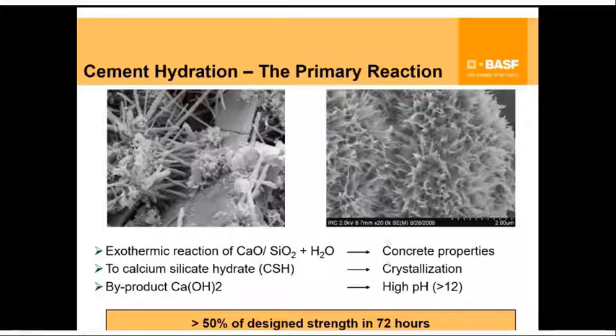Calcium silicates and aluminates in the cement react with water to form primarily calcium silicate hydrates. The aluminates, of course, form aluminate phases. One of the very commonly known phases is called ettringite, which is actually one of the first things that you see when you react cement with water. However, over time, you see growth of the calcium silicate hydrates. And this is ultimately what brings about a lot of the properties that we see both in the plastic state, but more so in the hardened state of concrete.